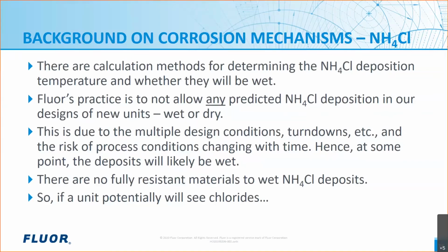So Fluor is very hesitant to design any unit with any kind of risk of ammonium chloride deposits. Another reason we don't want to risk these deposits is there's no fully resistant material to wet ammonium chloride deposits. It's not like we can say, oh yeah, there's a risk in the shell and tube exchanger, let's just upgrade the alloy. Even if you put in the best materials like alloy 625 or Hastelloy C, if it forms wet ammonium chloride deposits, there's cases where they've still had leaks.